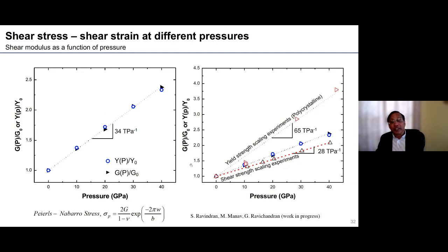And we believe one of the reasons has to do with the Peierls barrier at high pressures, how the Peierls-Nabarro stress varies, and this is something we need to look at in more detail in the core structure. Also the simulations which we have done are essentially single crystals. So we need to be able to account for grain boundaries and interfaces and other mechanisms associated with this. And this is work in progress.